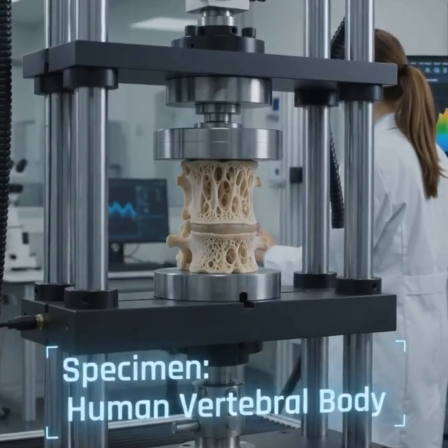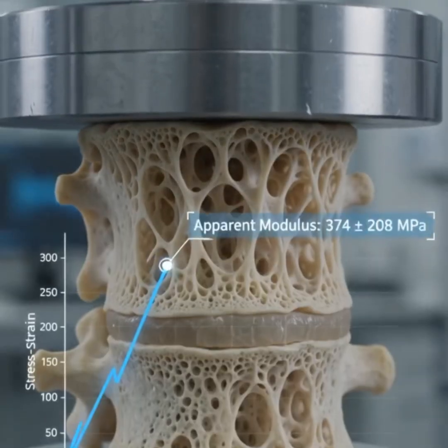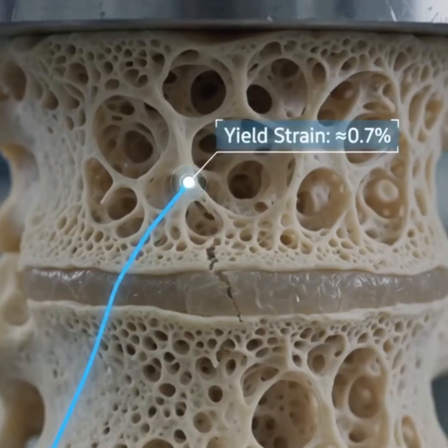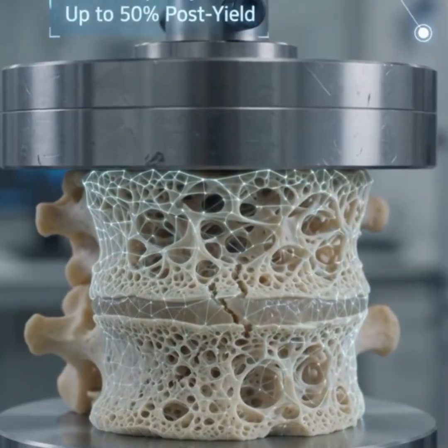We are testing a human vertebral body specimen. The apparent modulus averages 374 megapascals. Inverse FEM optimizes the damage properties.